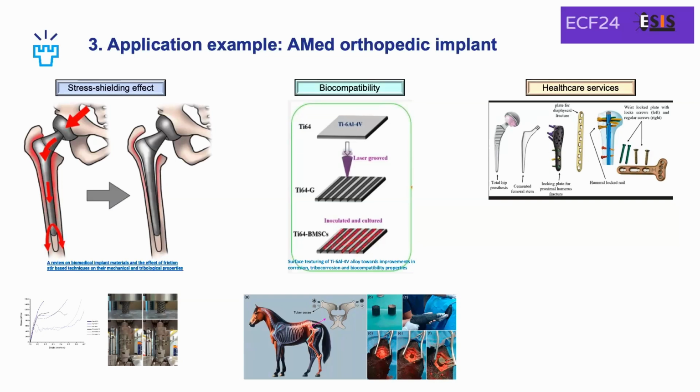We put those samples into horses. I'm sorry, the horses are not alive anymore, but the result showed that we were absolutely correct. We made an open structure with the idea that we don't need an implant to put any screws. We want the bones to grow through the implant so that the implant will finally be a part of your own body.